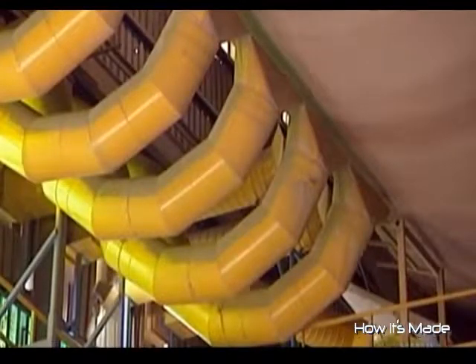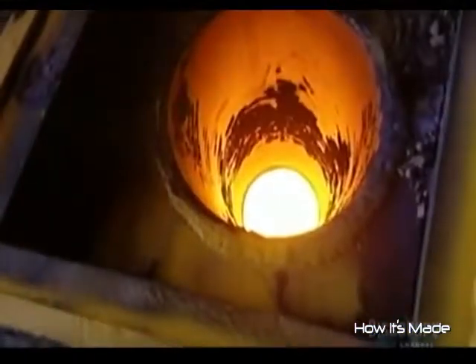It's set at an angle so that the powder moves from top to bottom a distance of 49 meters. The kiln rotates about 2 turns a minute to ensure the material travels through at the right speed. The burner's gas flame at the bottom reaches a scorching 1600 to 1700 degrees Celsius.